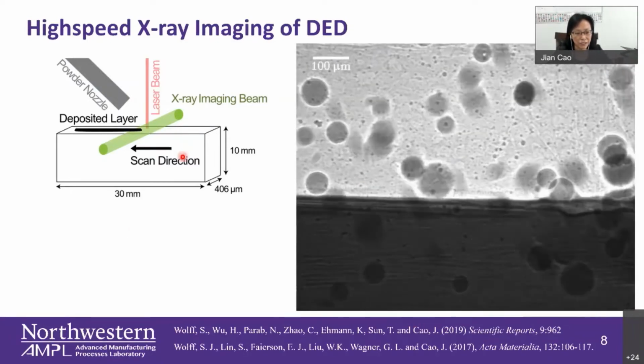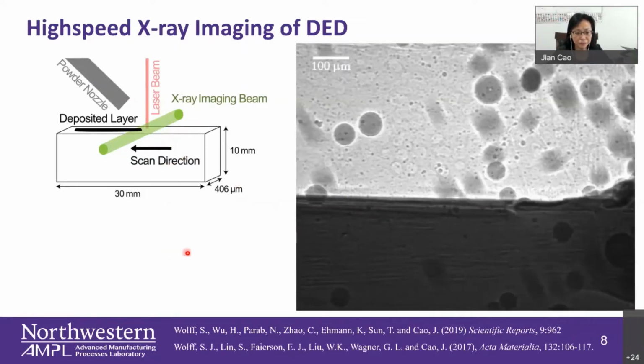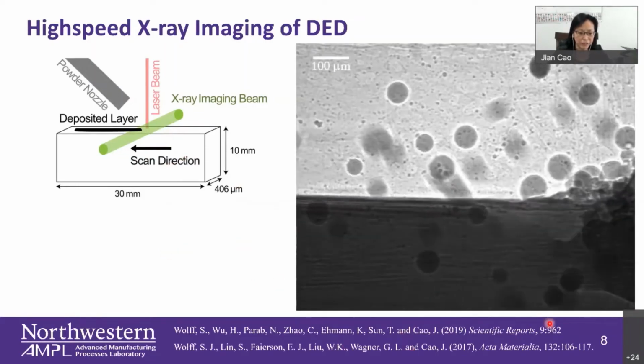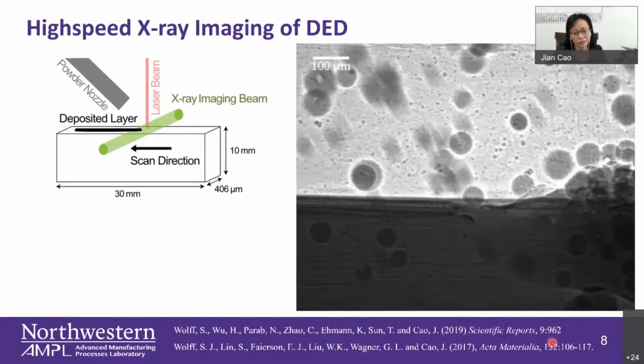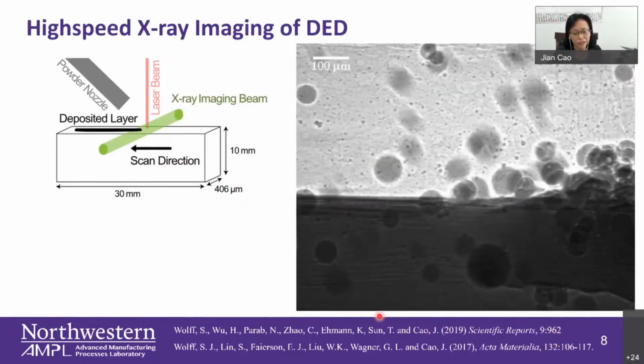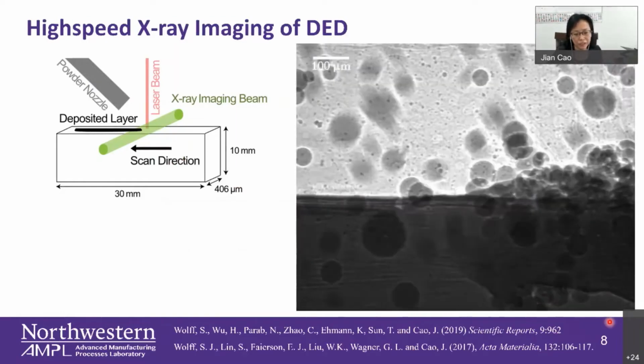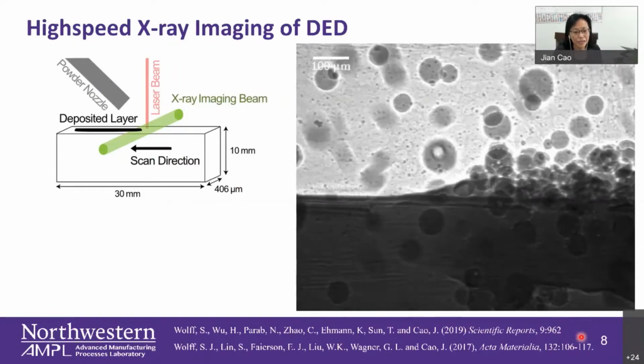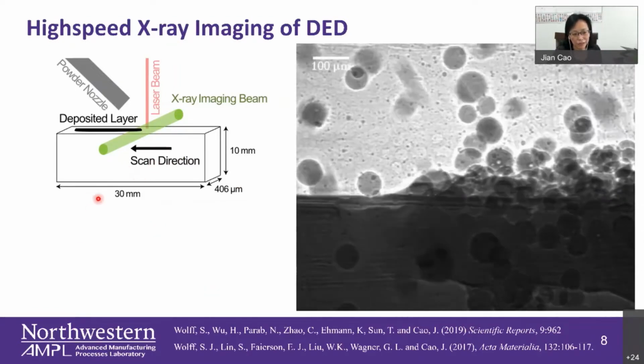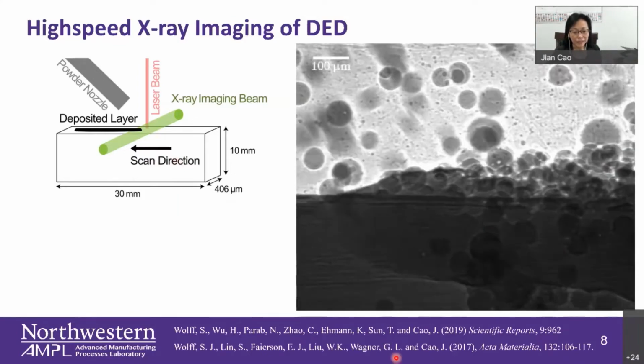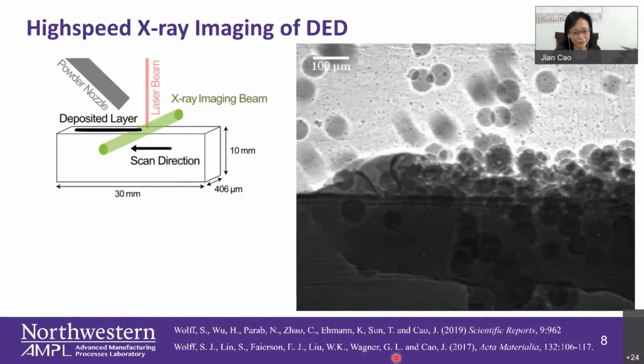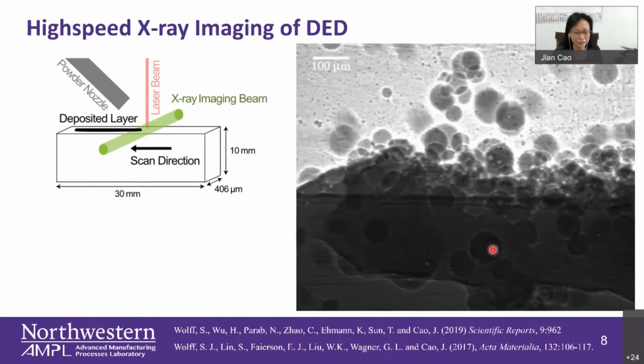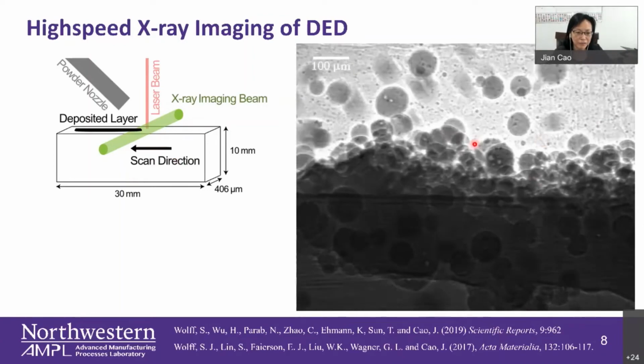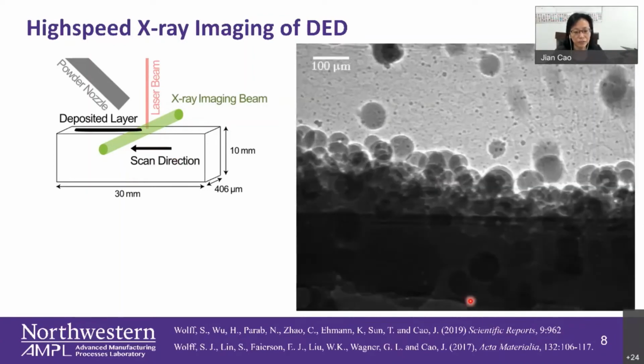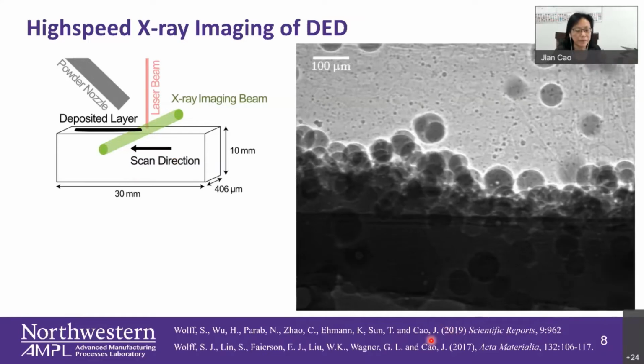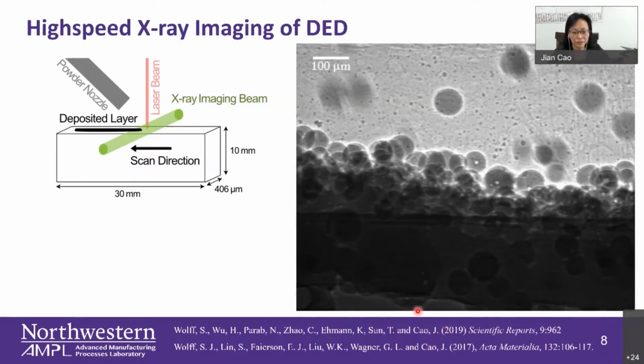So this is the X-ray imaging, high-speed X-ray imaging, and the frequency here is 80 kilohertz, and you can see, because of the different densities of the powders, fluids, and solids, the boundary right here, the melt pool. The X-ray is looking in this direction, the green direction. And you can see that this is a really very violent process, with the powder coming down, flowing out. The porosity was also coming from the powder itself, as well as lack of fusion, or other kinds of mechanisms.